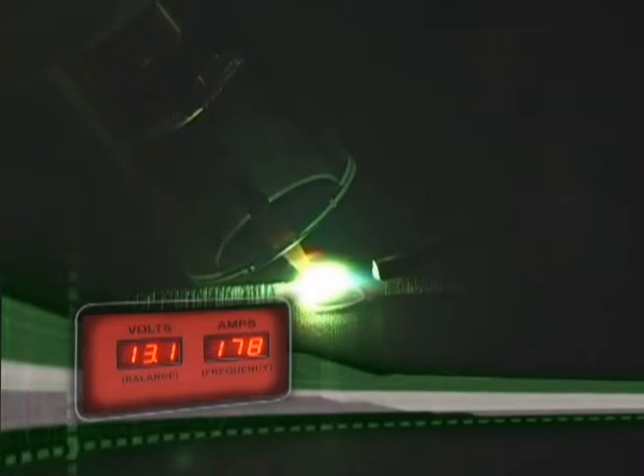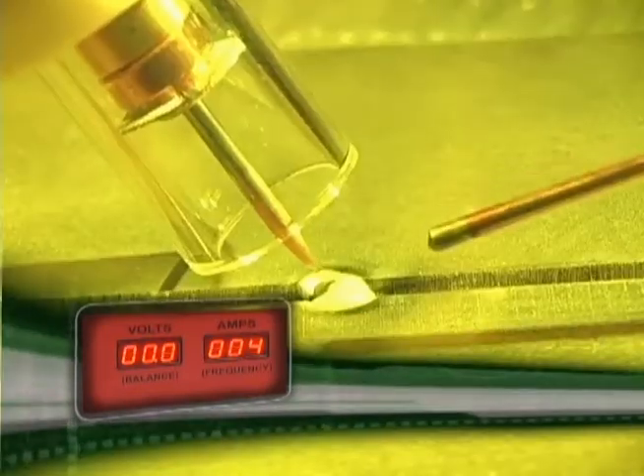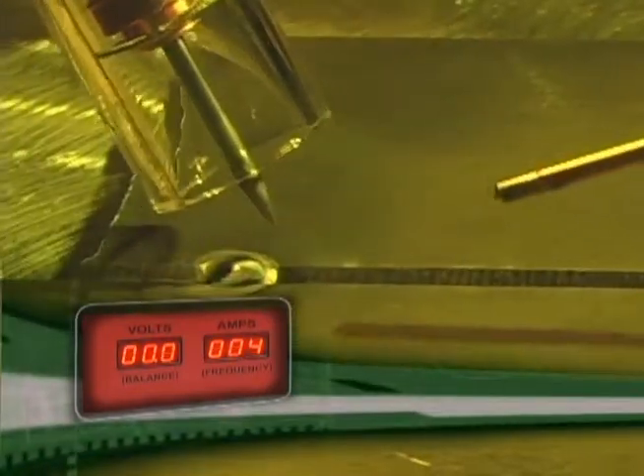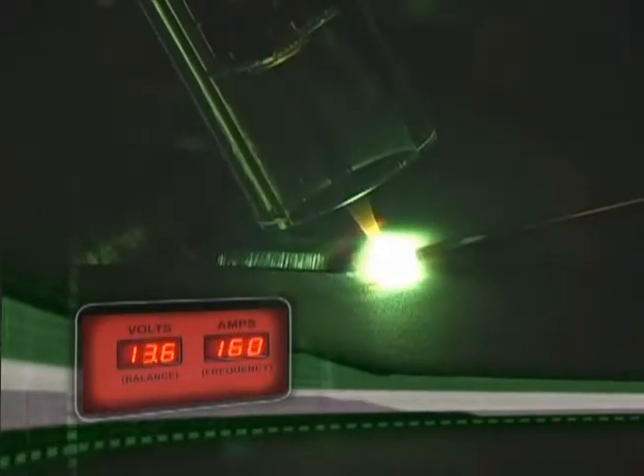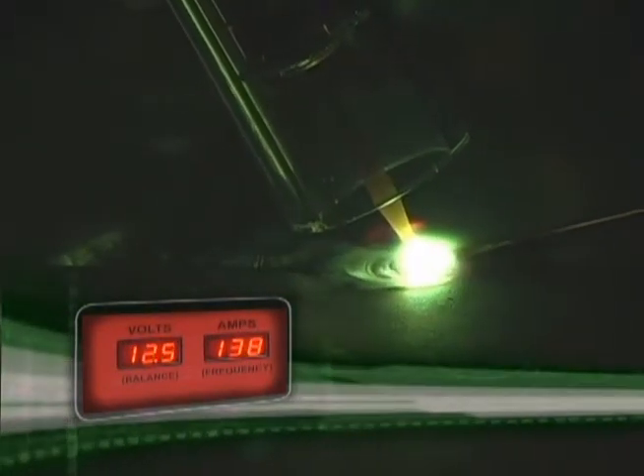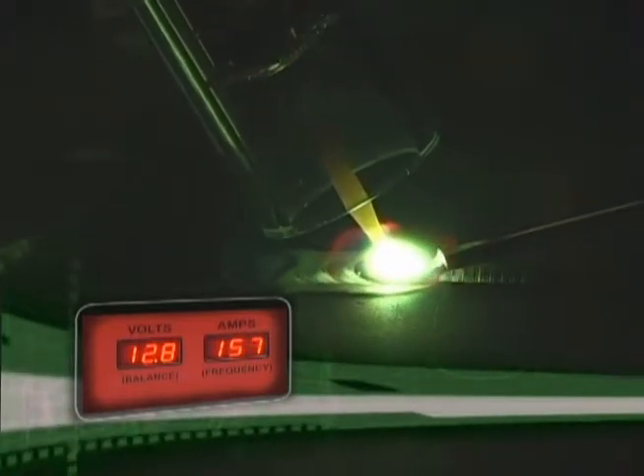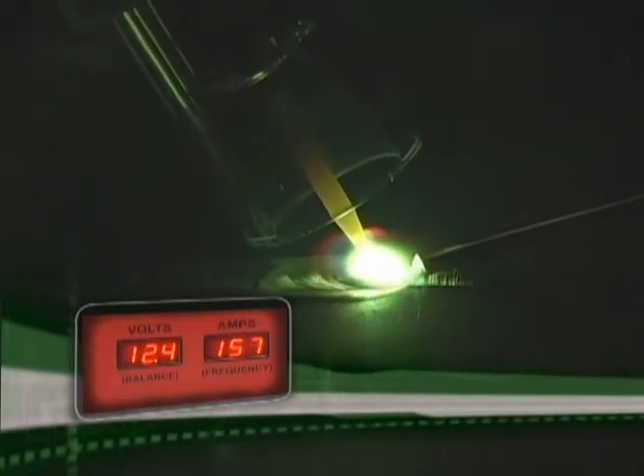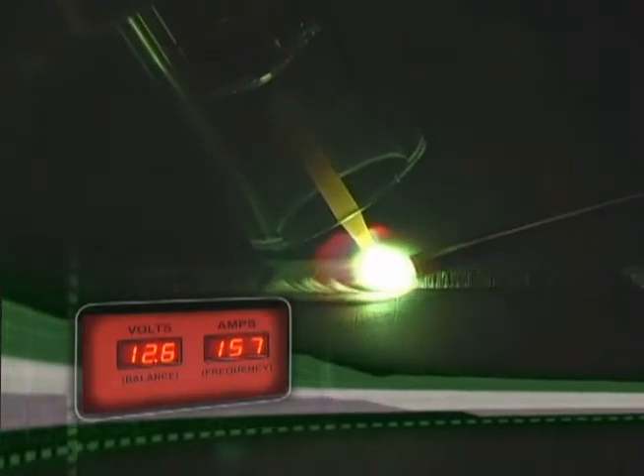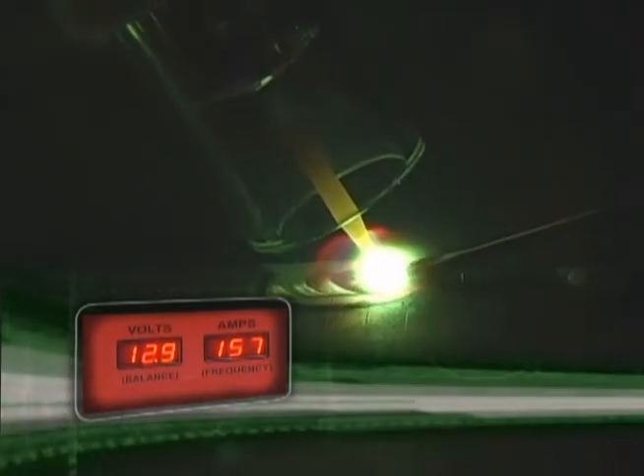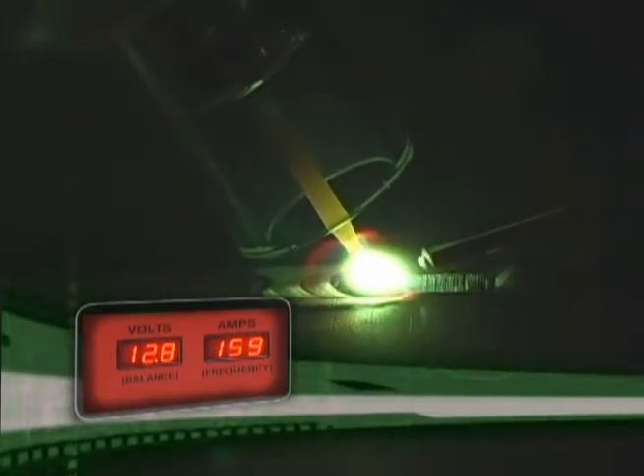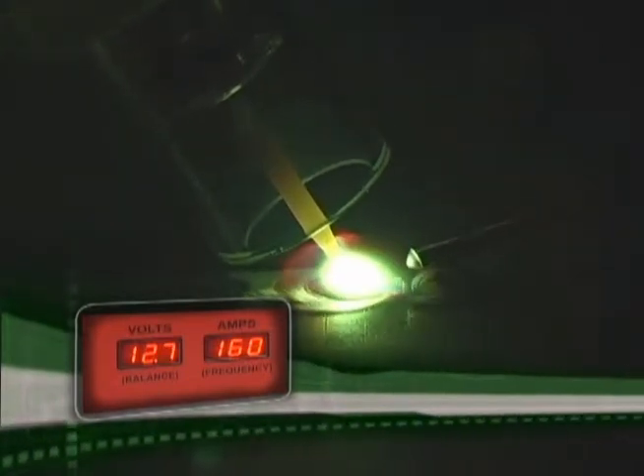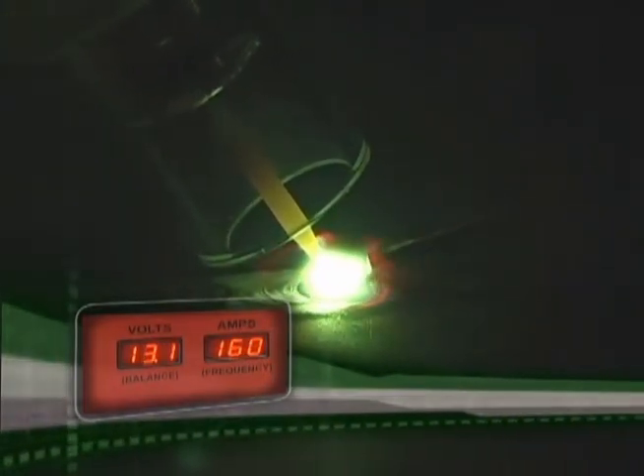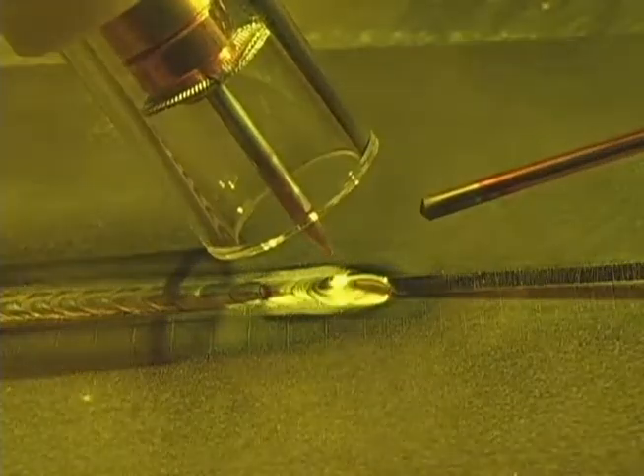Remember, the technique is the same whether you're welding sheet metal or 1/4 inch steel. The difference is we have to put more heat into the metal, which means more amperage. By increasing the amperage, you will have to take into consideration the effect the amperage will have on the tungsten, so we increase the diameter of the tungsten from 1/16 of an inch to 3/32 of an inch. We are running close to 160 amps and adding more filler metal, but again, the basic process is the same.